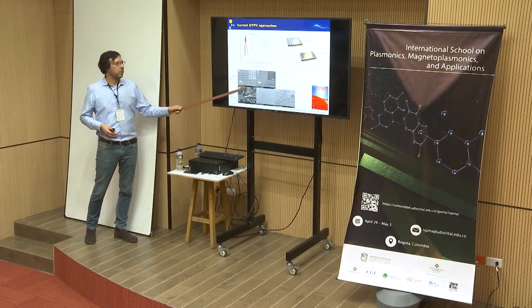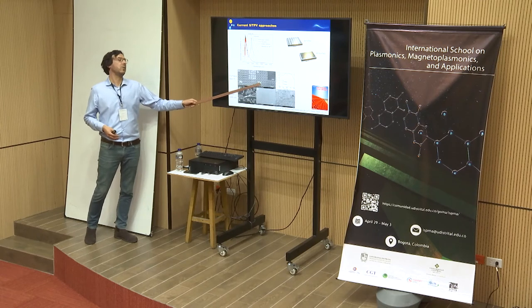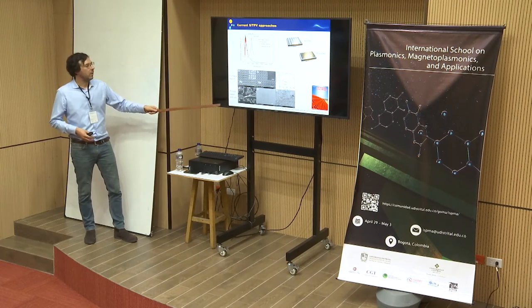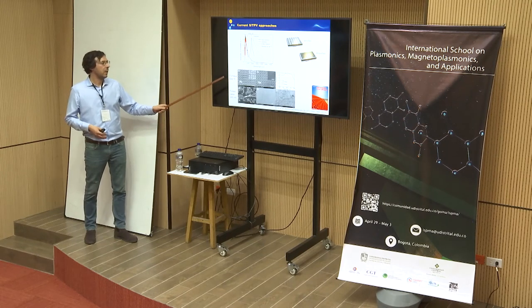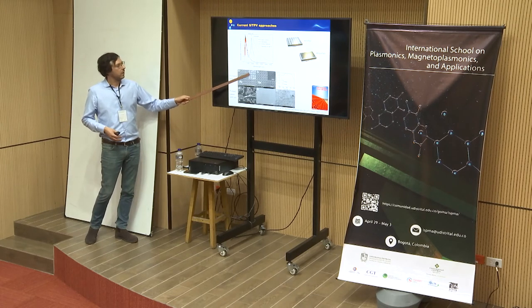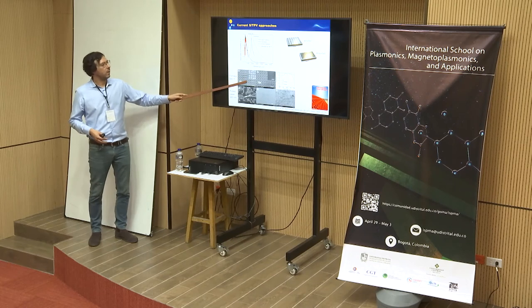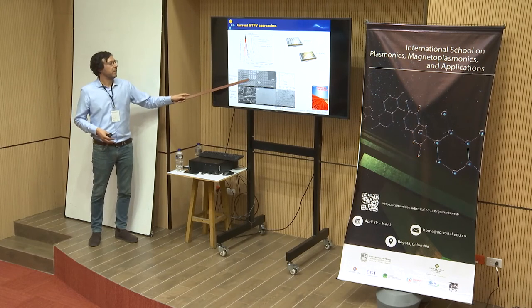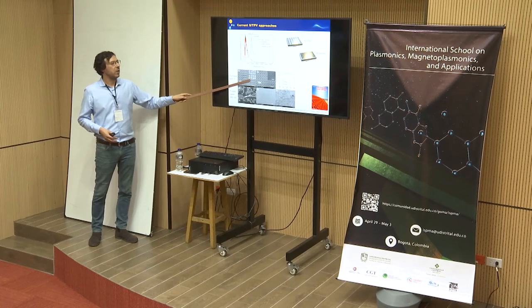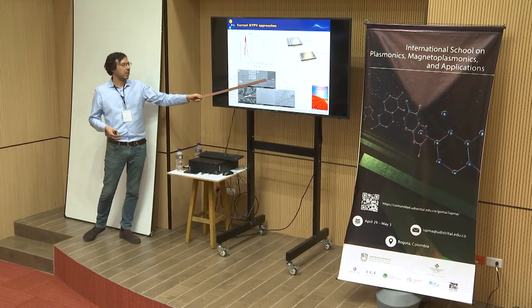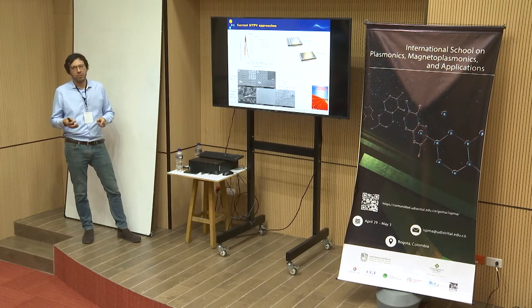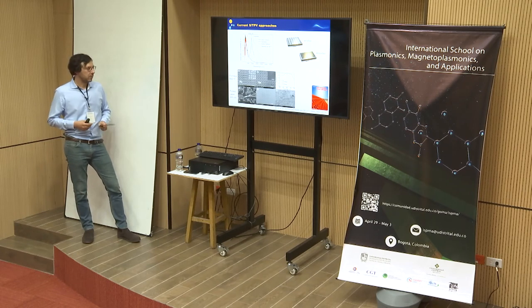And how, in doing this, you can really use metal nitrides, which are very much resistant to temperature, so they are refractory, instead of normal plasmonic materials like gold. You can see that by heating up to 800 degrees C, you really destroy the structure, because of the heat which is generated in the structure, which really changes the shape of your antenna, while otherwise with metal nitrides you can retain the structure, and therefore you can retain your selective emittance or absorbance in the device.